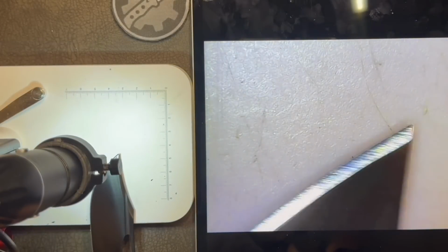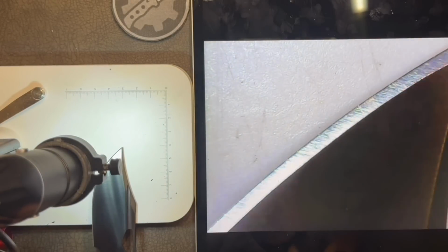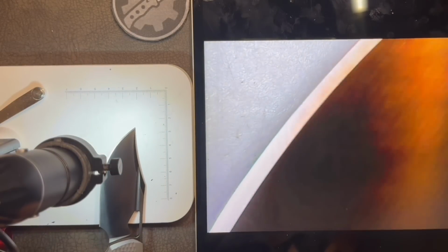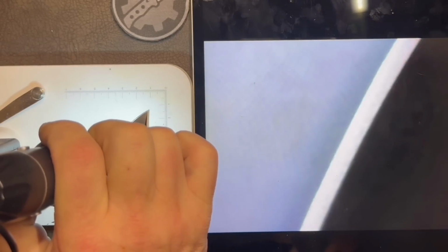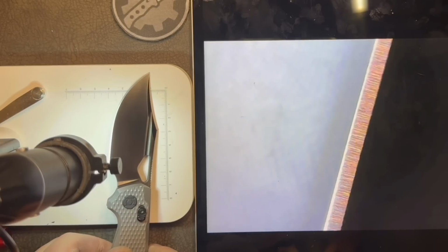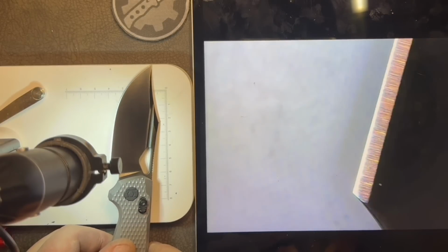Let's put it under the microscope and start with the tip. That will tell us a lot about how professional the person who sharpened it is. And by the looks of it, the tip is in great condition. Clearly the knife was stropped, but not excessively, so the tip didn't get rounded off, and there's only a little bit of convexity near the apex. I do notice that the width of the secondary bevel varies by a small amount, and that means that the edge angle is varying as well, perhaps by 1/4 of a degree.